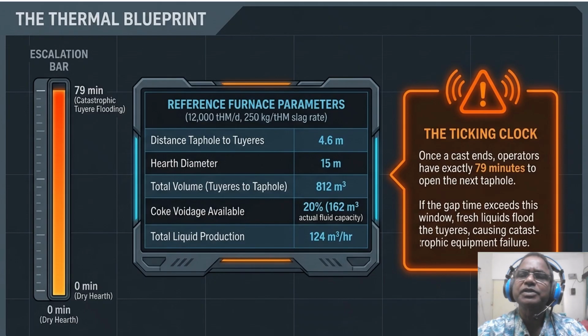So this slide represents our reference furnace parameters for 12,000 ton per day operation. So look at the escalation bar on the left. It starts at 0 minutes with a dry hearth and hits at 79 minutes for catastrophic tuyere flooding.